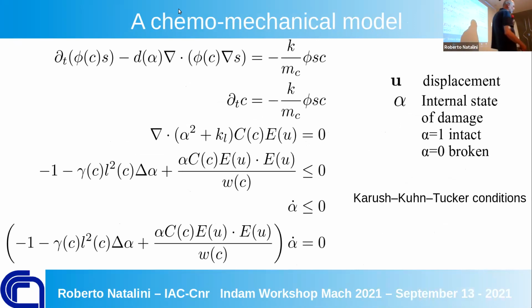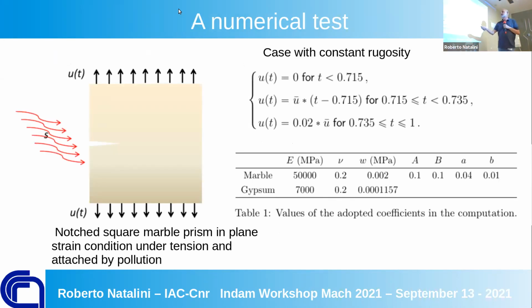Another idea is the chemo-mechanical models. I mean, we introduced something which is the internal state of damage: 1 if it is intact, 0 if it's broken, the stone, and you introduce some relations, some equations to say the mechanical state of our specimen. Here, for instance, that's a test on a marble prism, and you have a stress applied on the top and the bottom, and you have here a sort of notch to start the damage, the fracture in this part,